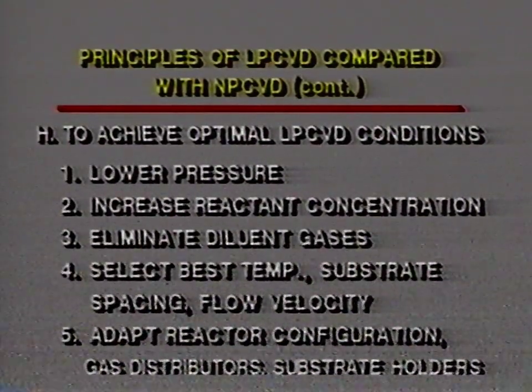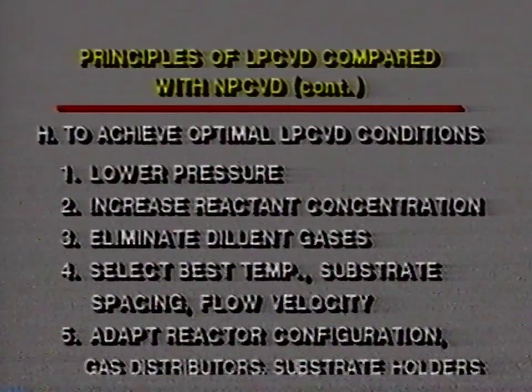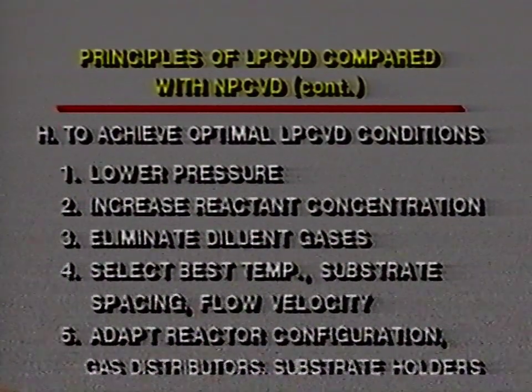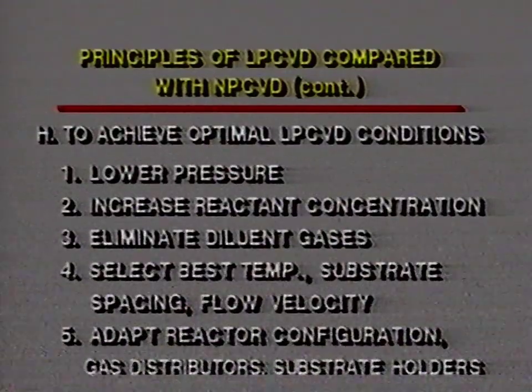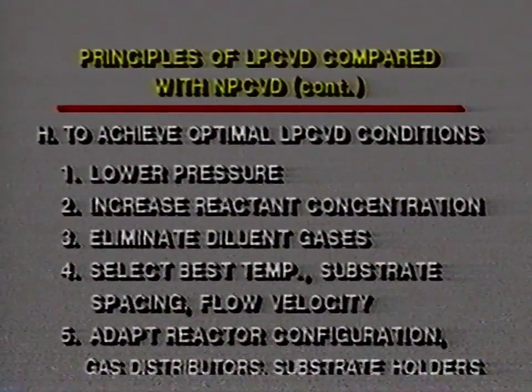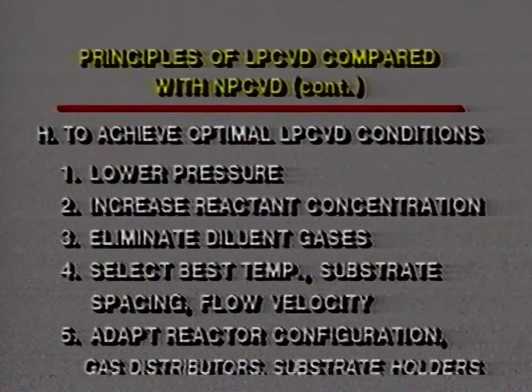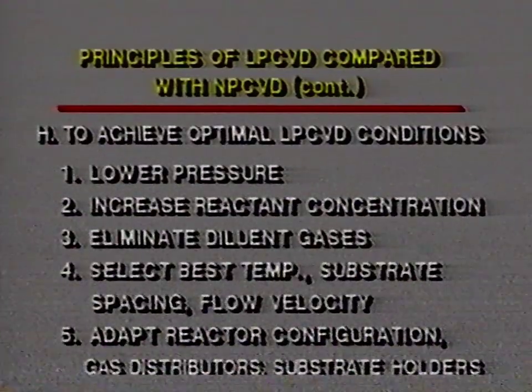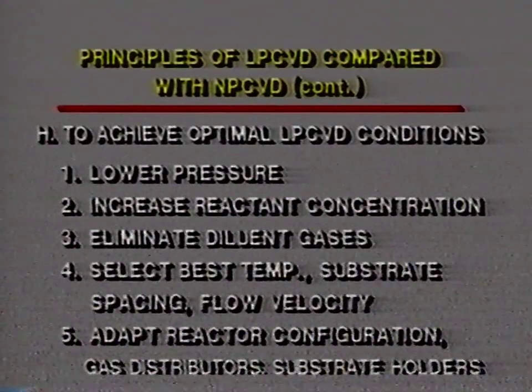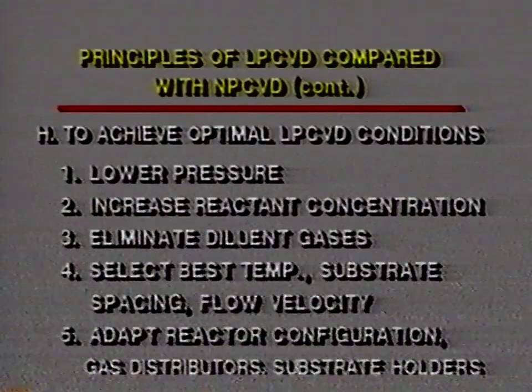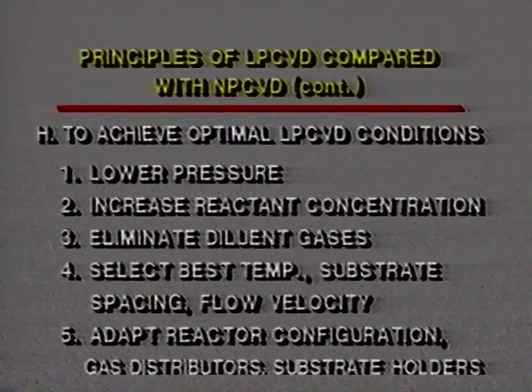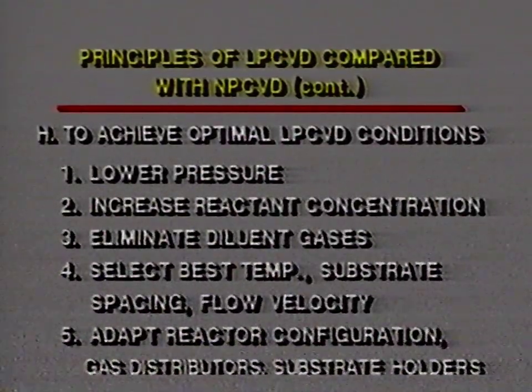Again, we can do with fewer reactants and less diluent gas. And finally, we have to select the best temperature, which may involve some ramping of the temperature profile to get a profile which is conducive to uniform film deposition. That is, we may have to ramp the downstream end of the reactor tube by 5 or 10 or so degrees to compensate for any depletion effects.